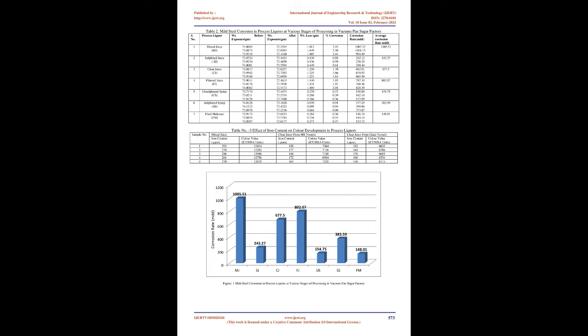Corrosion in filtered juice. Mild steel corrosion was found to be considerably higher, i.e. around 800 mdd, mainly due to lower pH and higher temperature of the filtered juice. It can be observed that mild steel corrosion rates in filtered juice are higher than those in clear juice and somewhat lower than those in mixed juice. Moderate quantity of dissolved oxygen in the filtered juice also contributed towards higher corrosion.